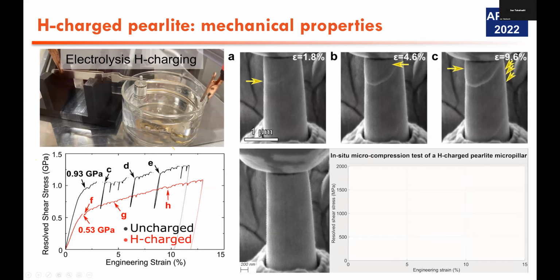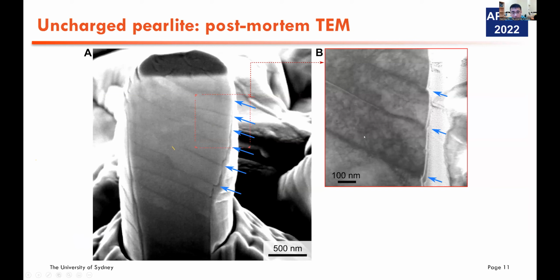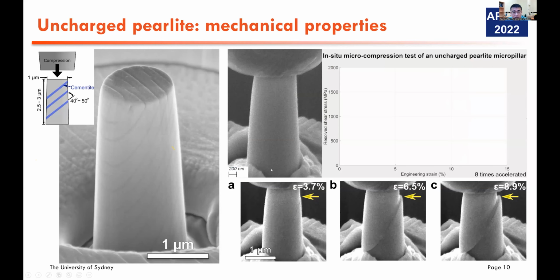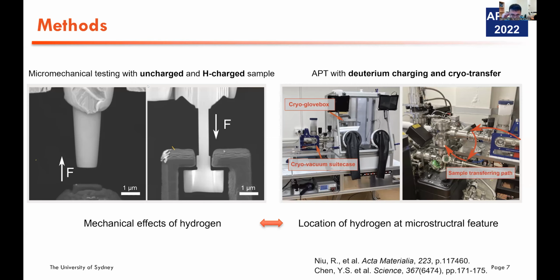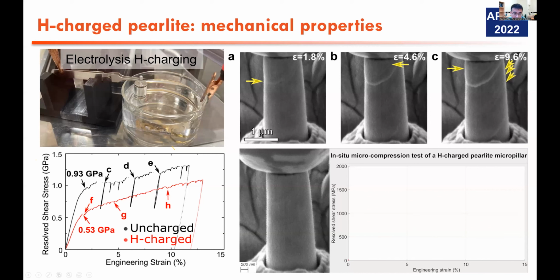Yes, but for in situ charging, we conduct the charging on the tips. In this situation, we charge the tips with 2.2 volts for around 30 seconds. And we believe this charging condition oversaturated hydrogen in the atom probe tips. That's why we observe a very high concentration in the atom probe data.